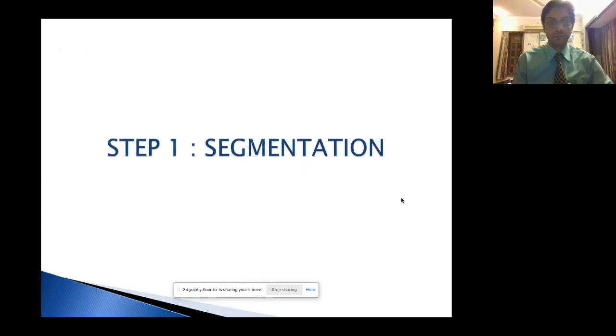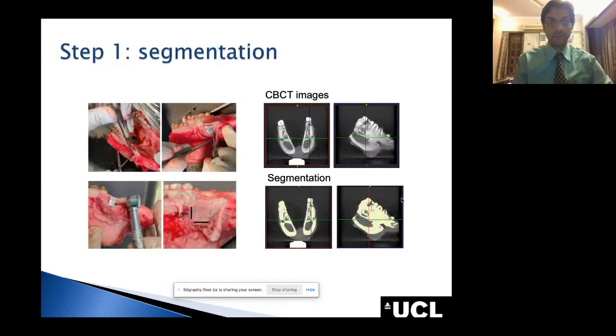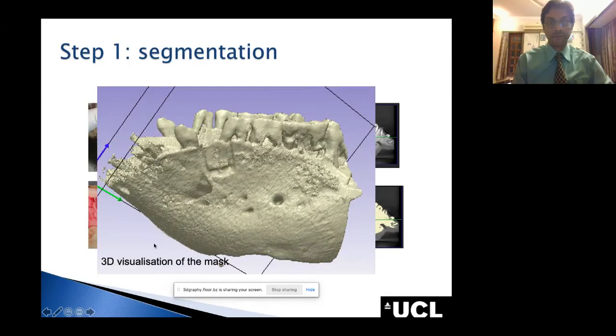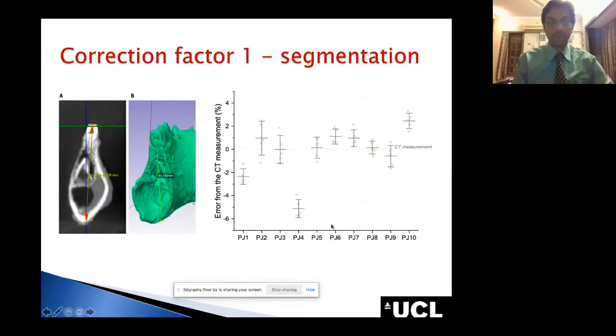So the first step was to do the segmentation, so the selection of the regions of interest. After making the template defect, which was 1 centimeter by 1 centimeter on the lower pig jaws, and after taking the CBCT of the pig jaw, we segmented it, and we obtained a 3D visualization of the mask, as you can see here. This was done by using a thresholding tool in the image processing software. But the problem is that it is really dependent on the user experience and on the amount and levels of thresholding used and intrinsic properties.